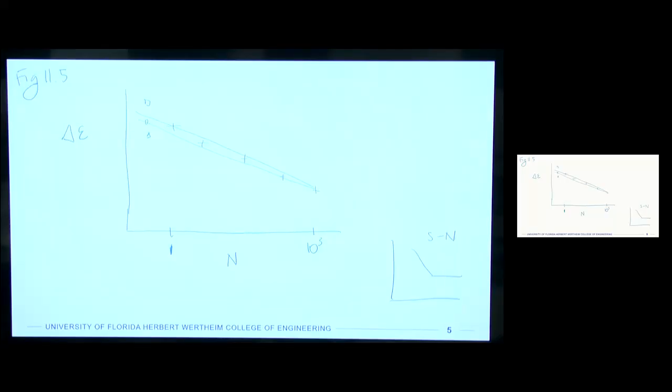But for these types of experiments, the slopes really don't vary that much. And so they said, okay, if we're just going to fit kind of one line to all of this, and this is a log-log plot, then we'll say that it has a power of kind of minus 0.5, right, for all of these. And that turns out to be refined in this chapter, so don't take that as the gospel, but that's kind of a guideline.